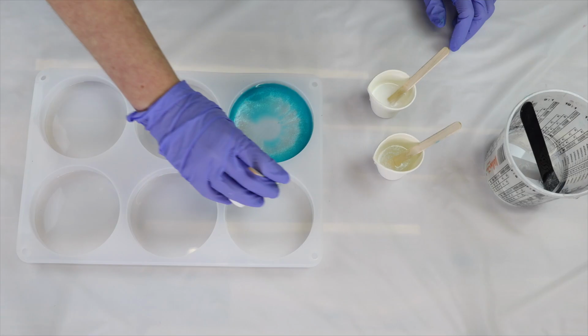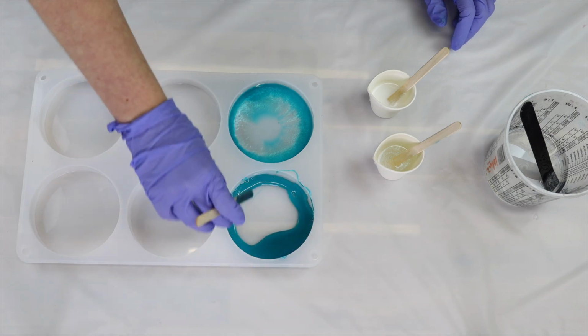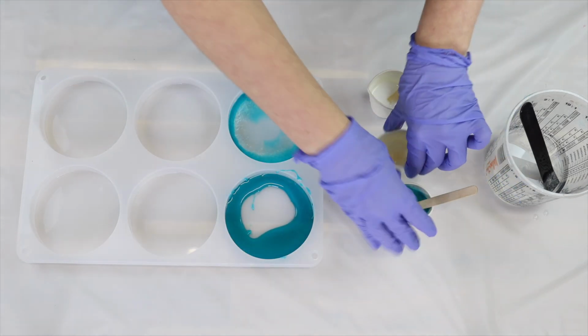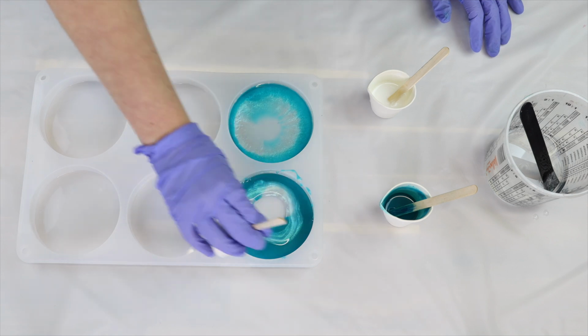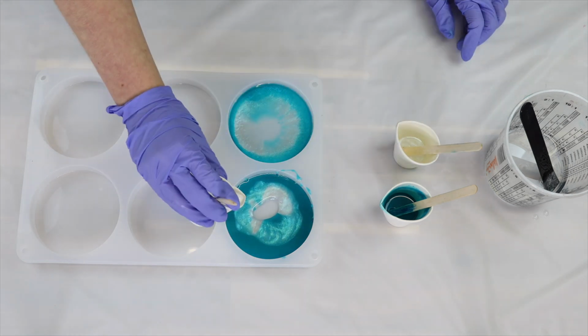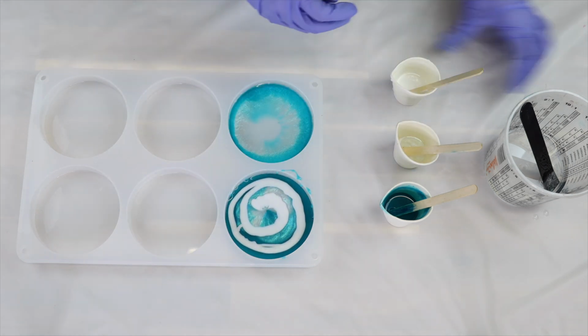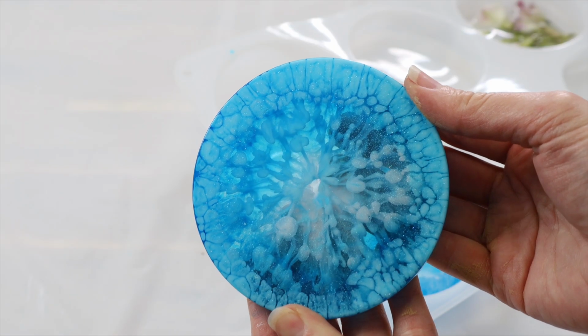But if I put my tint and my powder down first, because they are lighter, and then I pour my heaviest pigment at the end, it then has the ability to push down through the tint and the powder colored pigment, powder colored resin, and therefore it can create some really cool effects.